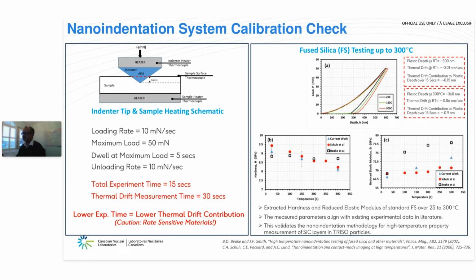Similarly, at 300 degrees C, the plastic depth for the fused silica measurements at 50 millinewton maximum load was about 360 nanometers, and the thermal drift that we measured was slightly higher than at room temperature, minus 0.06 nanometers per second. But for 15 seconds of experimental duration, the total contribution of the thermal drift to the plastic depth was still less than a nanometer, which I consider insignificant.